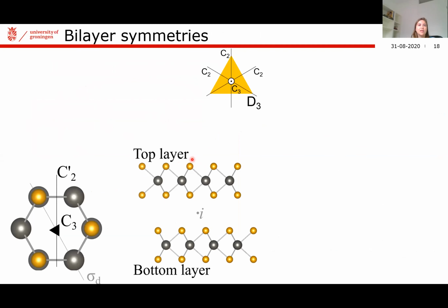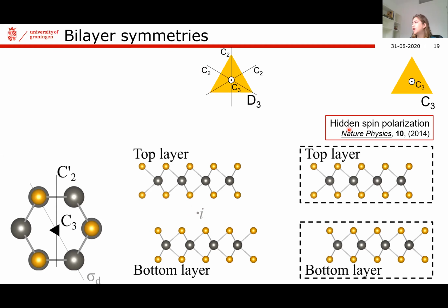Now, what happens when we look at the bilayer? Strictly speaking, the main difference in symmetry between a bilayer and a monolayer is that the bilayer has this inversion point over here. And that would mean that we cannot observe any spin valley coupling for bilayers. However, it's been proposed theoretically already a few years ago and shown for various systems that even in systems with inversion symmetry, sometimes something called a hidden spin polarization can arise, where this spin valley coupling is preserved in subparts of the system. And this is exactly what happens for